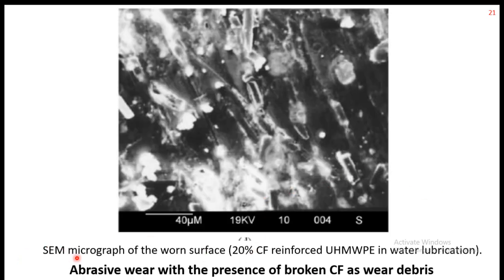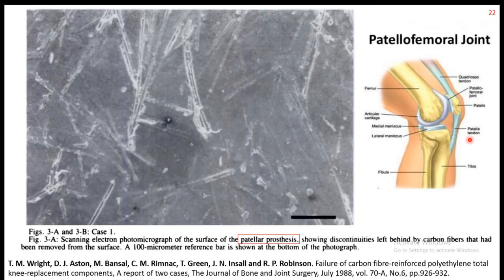Here you can see SEM micrographs of one surface, 20 weight percentage carbon fiber reinforced UHMWPE in water lubrication - this is the previous data I showed you. But here we can see that, of course, UHMWPE will deform by plastic deformation, but we also see some fiber pullout. This kind of fiber pullout may not be very good for implants, because these fibers will act as wear debris, or the body will react to the presence of these carbon fibers.